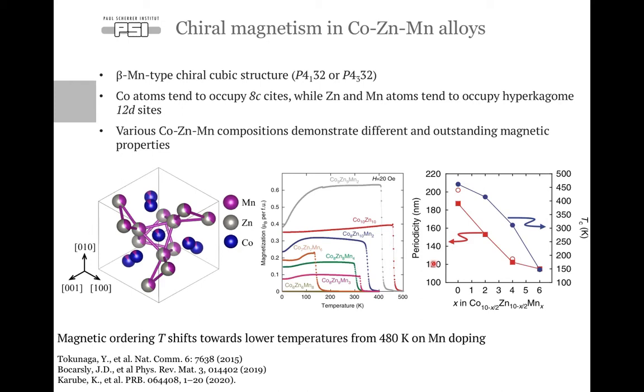At the same time, the periodicity of the magnetic spiral, which is the result of the competition between symmetric exchange and antisymmetric Dzyaloshinskii-Moriya interaction, can be pushed from around 200 nanometers in the 10-10 compound down to around 100 nanometers in the 7-7-6 compound, simultaneously with the decrease of the ordering temperature from 480 K down to around 150 K.